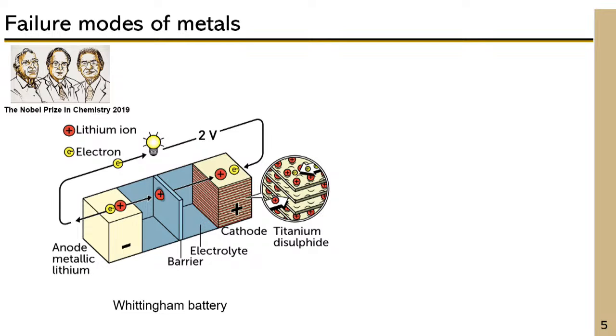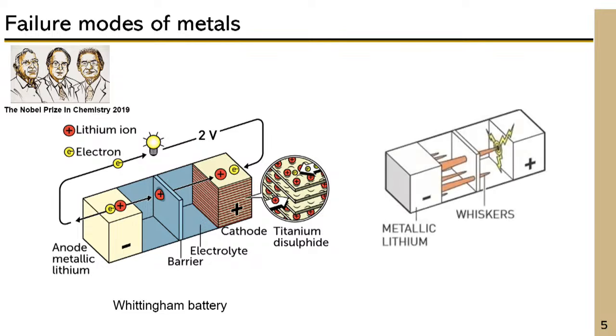Now, you might ask why we don't see these kinds of batteries nowadays. The major problem they faced was whiskers that started to grow on the metal side. If these kinds of whiskers grow over time, they can penetrate through the separator and reach the other side of the electrode, causing a short circuit. And that can lead to catastrophic failure in the battery.